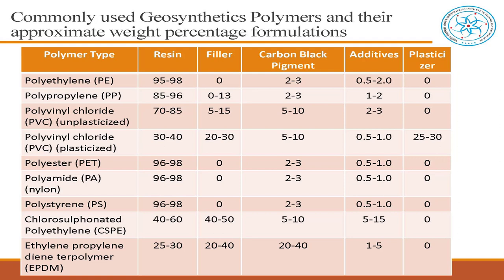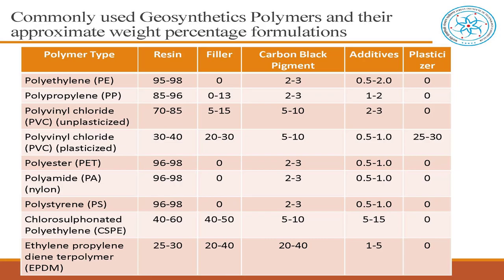The first important point is we are going to use first-grade virgin materials — not recycled. The polyester used in geosynthetics is not the same as shirt polyester. It has additives to better perform — higher strength, higher modulus, or thermal resistance. So when you say polyester or PVC, it is not always a pure form; it always has some additives. Minimum, there will be 2 percent carbon black.